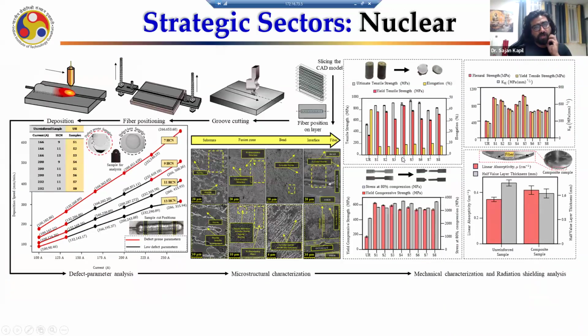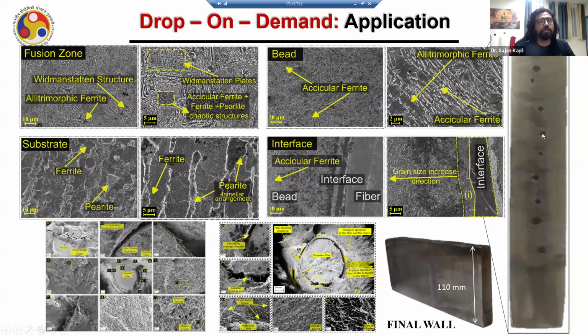We thought if we put tungsten, there may be an application in nuclear, but till now I could not reach the right industry where I can propose this. I can put tungsten into the wall because tungsten absorbs radiation. But I can give shape also to that tungsten. I can make a circular cylinder which has 40% loading of tungsten in mild steel. It will be strong as well as maybe absorbing nuclear radiation, but maybe some other applications as well. Happy to hear if you suggest something. You see this wall? These dots are tungsten fibers, and this is only 12%. We are going to publish one more paper on how to load 40% tungsten into mild steel.